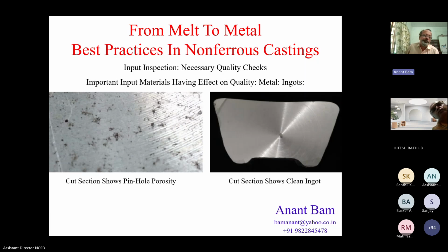The cut section which I was talking about: a cut section of the ingot, finely machined. On the left-hand side, you can see that there is a lot of pinhole porosity in the ingot. That means a lot of hydrogen was already dissolved in the metal during casting or making of the ingot. That puts excessive load on the foundry in metal treatment for degassing. So we have to avoid and reject such ingots. On the right-hand side, the machined cut section shows a very clean and smooth surface finish without any visible porosity. That we call a class A ingot. So it's a good, acceptable ingot, provided the chemistry and other things are accepted. Next slide, please.